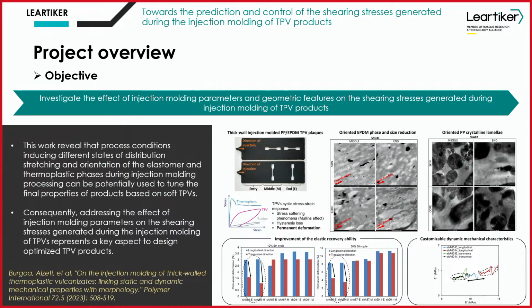So this is good to have better elastic performance properties in the anti-vibration components, and we are even able to somehow tune the dynamic characteristics or vibration damping characteristics of the final component. So that means that addressing the effect that the injection molding parameters have on the shearing stresses that are generated during the injection molding represents a key aspect to design optimal TPV products.